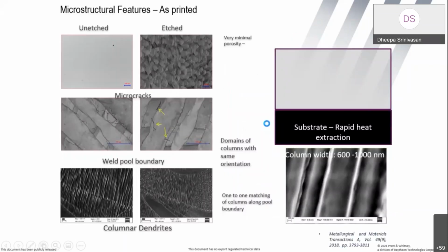So of course we went on to analyze the as-printed structures, and you can see here a dense sample without HIPping. You can also see the etched microstructure here. And then we went on to observe whether there were any micro cracks. Yes, there were some micro cracks. It is impossible to make a material without any defect at all.